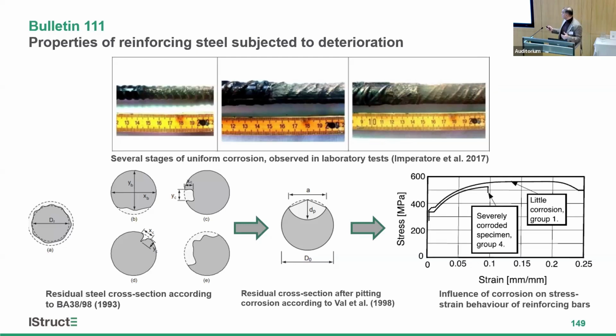But also corrosion actually changes the behavior of the material. It doesn't change the behavior of the parent material, but the reason it is changing is because for a given length, you have got non-uniform pitting. So wherever the minimum cross-section area is starts yielding under the tensile force, and then the other one starts yielding. So this effect is essentially changing the behavior, and you can get localized yielding.